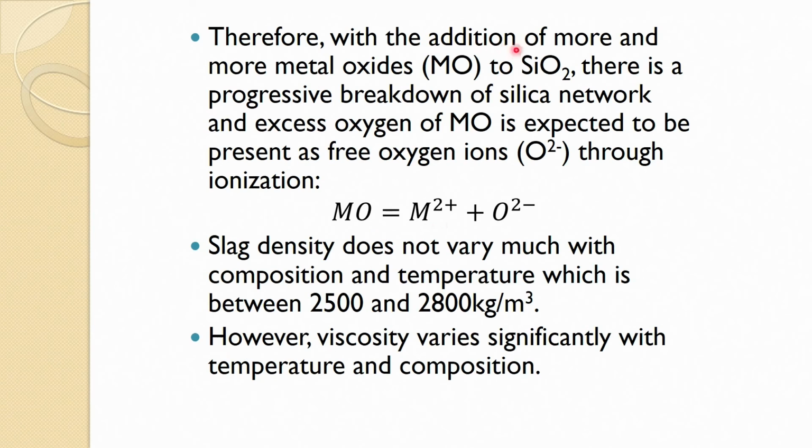Therefore, with the addition of more and more metal oxides like MO to SiO2, there is a progressive breakdown of the silica network, and the excess oxygen of the metal oxide is expected to be present as free oxygen ion, through ionization: MO equals M2+ plus O2-.